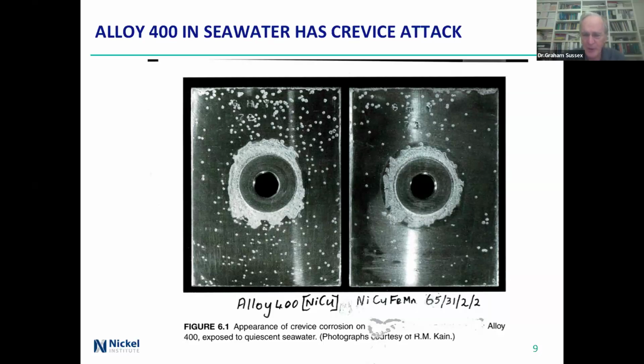All those spots around it are where corrosion has started, proceeded for a while, and then stopped. So when you scrub that up, you'll find that you're looking at bare metal underneath. And that's quite a useful thing for an alloy. But remember, it only works in a reducing environment. So the initial corrosion, this is just corrosion, will continue, but not at a great rate. And that was - I scrubbed it out - it was actually for a year's exposure.